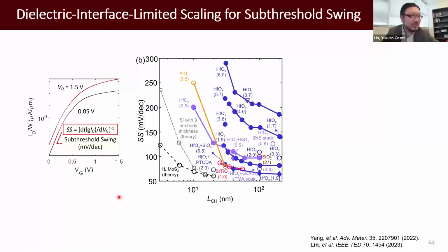Ideally, SS should be 60 millivolt per decade. For all non-ideal cases, that makes this bigger. So theoretically, we can see some benefit if we compare silicon and the monolayer MoS2. The SS can be suppressed at a lower gate length, but all these points are the experimental data, so we